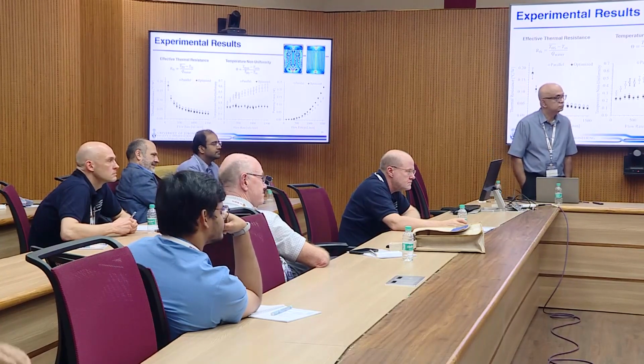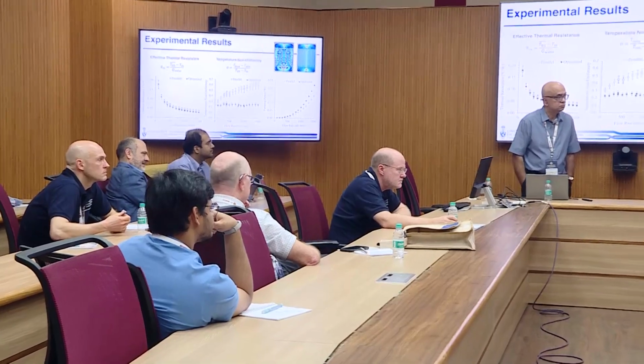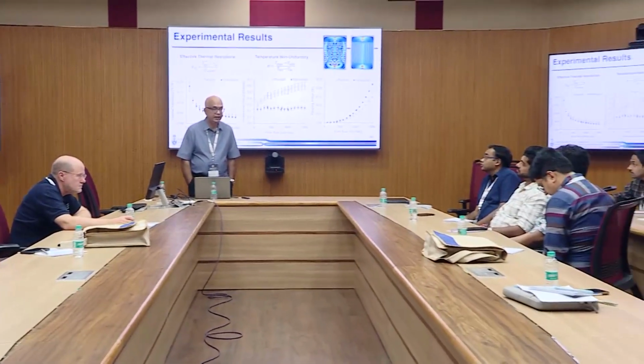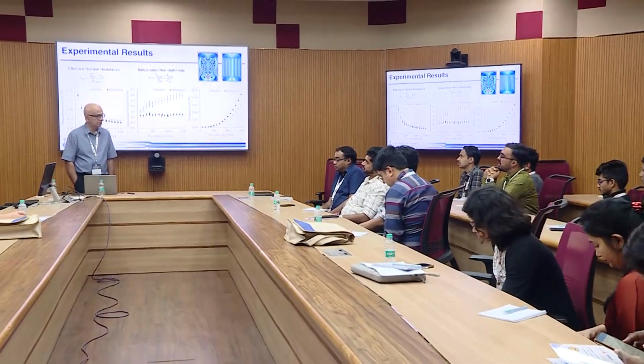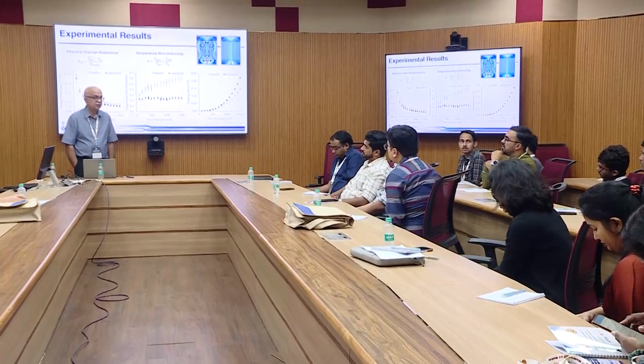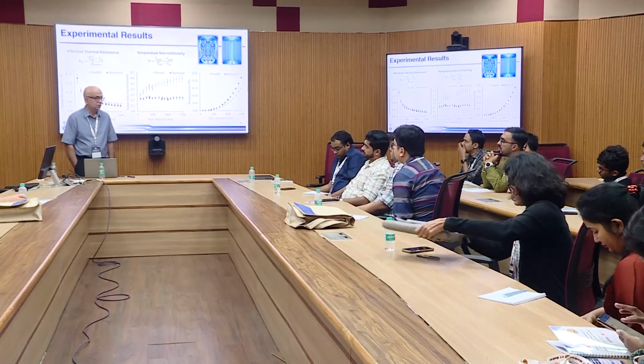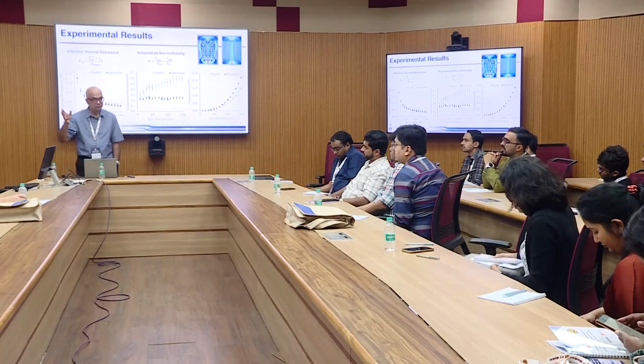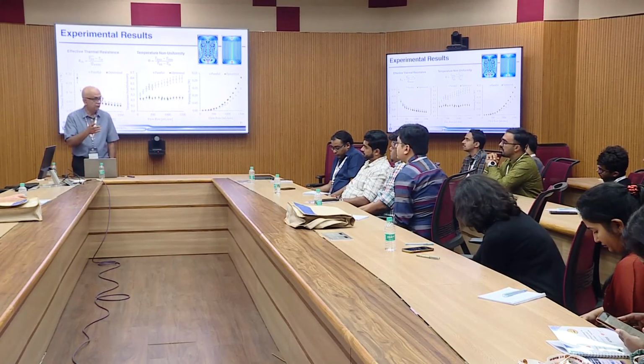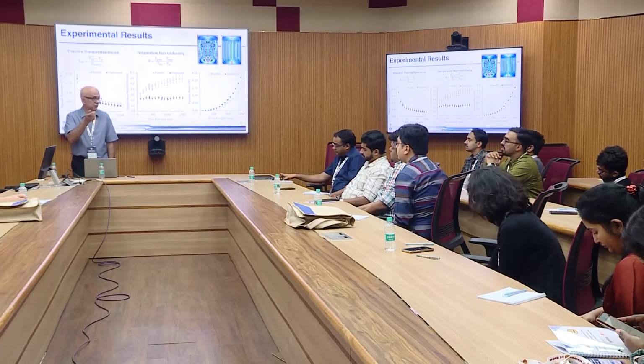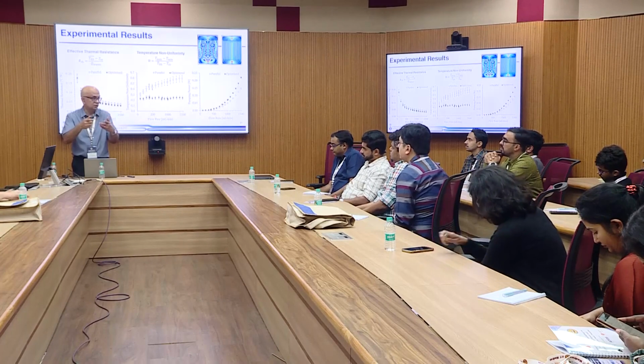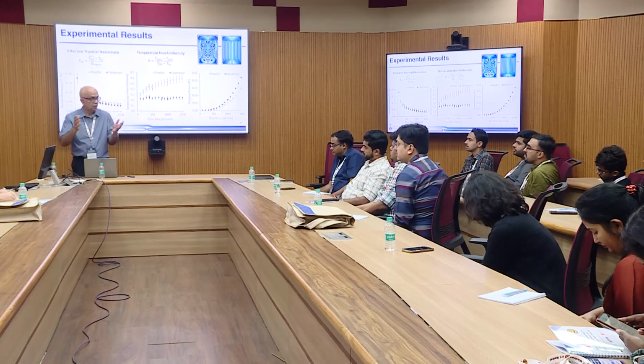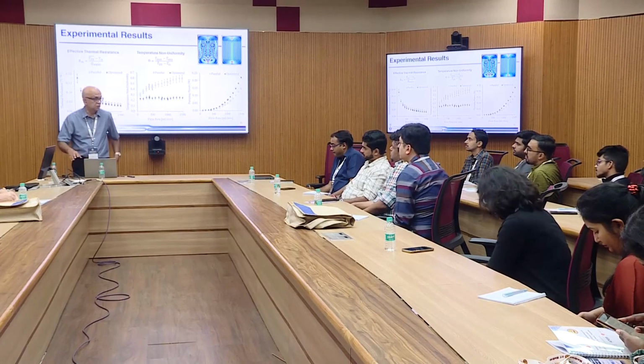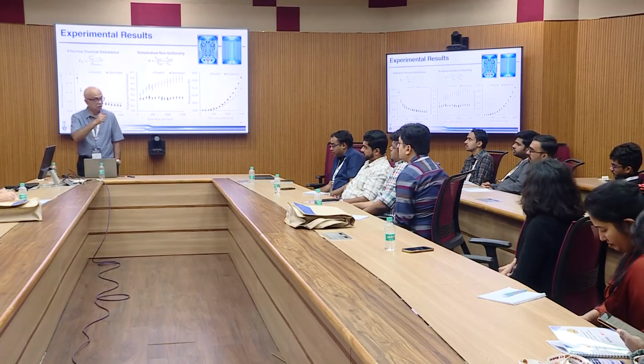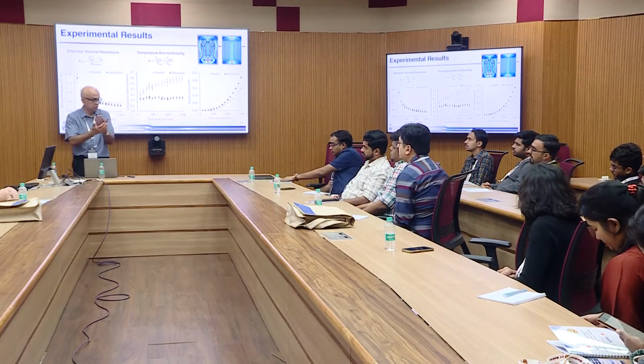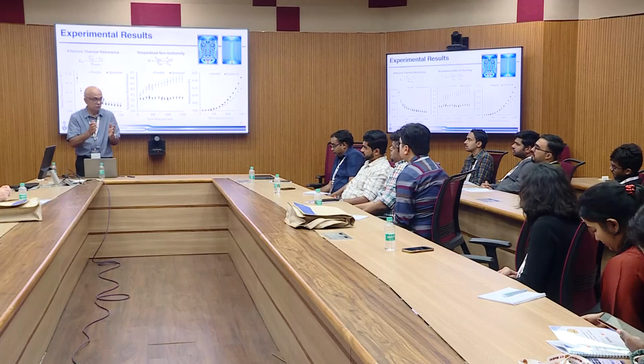Would there be any introduced porosity at the junction where the coating is attaching to the base material? In the coating itself, you get about 2% porosity. We've done a lot of work to increase that porosity. With Marco, we made heat pipe wicks and got a porosity of up to 44%. You can do it by putting two metals inside and then dissolving out one. We can make very nice wicks for heat pipes using this technique, and the advantage is that it's really bonded to the substrate really well. You don't have to worry about that.